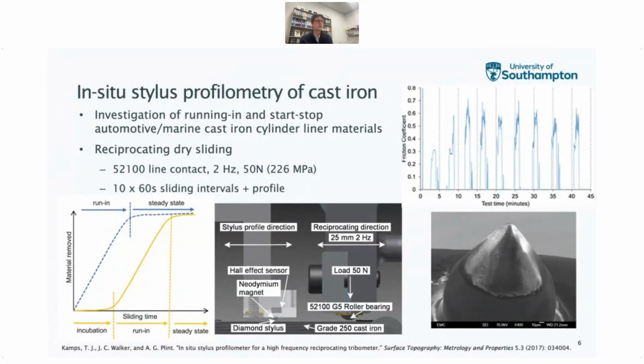And so we did this again on a cast iron surface, and we had various sliding intervals. So it was a start-stop test where you would slide for a minute and then profile the surface and then recommence the sliding. But without disturbing the surface, you would actually bring the diamond stylus into the contact, make your profile, and allow it to continue.